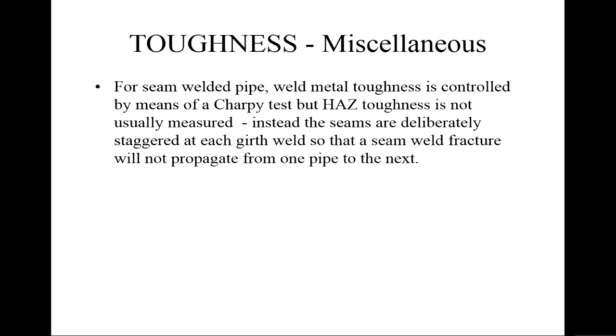So I've had student projects, in the Pipeline MSc, trying to do a set of Charpies through a weld to look at these heat-affected zone effects. And because your weld isn't vertical, it's this sort of shape, you've got different amounts of weld being sampled by each case. The tip of the Charpy is not always at the same position with respect to the material testing. You can get almost any result just by moving things a little bit. So if we had a localized test, it would be really good to do it, but we don't. So when there isn't a good test, people don't tend to do it. Doesn't mean to say it wouldn't necessarily give you some useful information if it could be done.